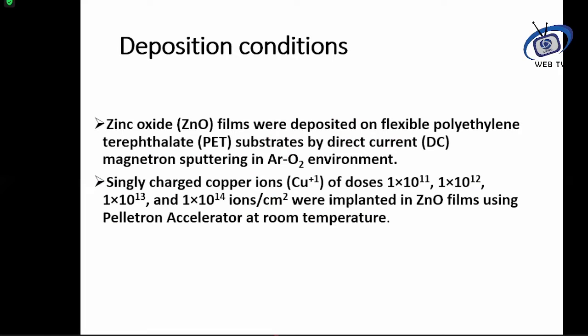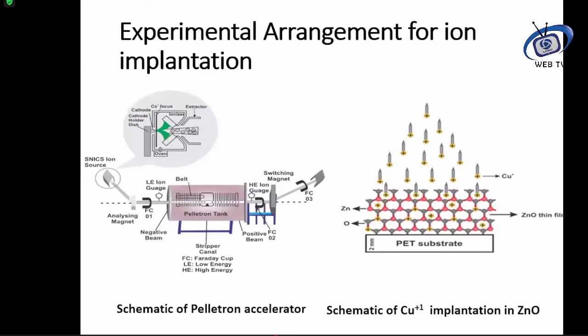So we deposited film under the argon oxygen environment, and then we implanted using the Pelletron accelerator for 4 different doses, and this is the setup. We deposited zinc oxide onto the PET surface, which is the flexible film, and then implanted copper ions onto the substrate.